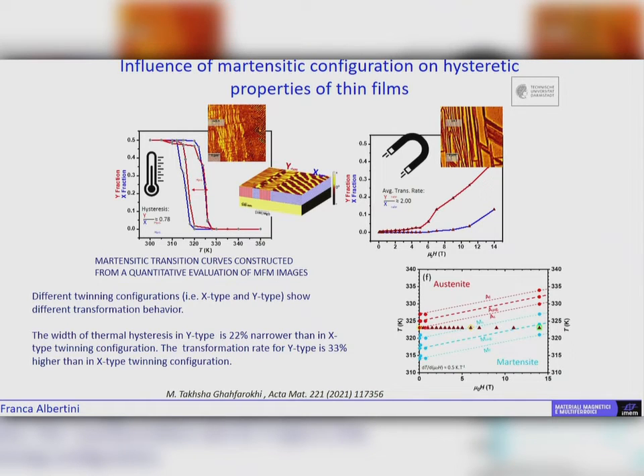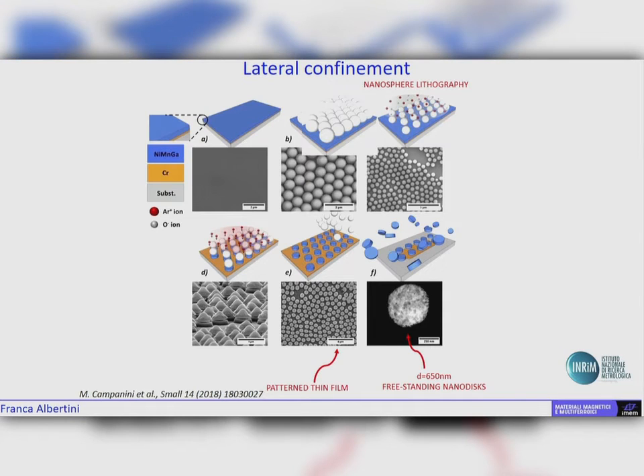And we have seen that the different twinning configurations show different transformation behavior, and that the width of the hysteresis, that has to be reduced as much as possible, is 22% narrower in the one kind of microstructure than in the other. And also, in this case, the transformation rate for Y-type is much higher than the transformation rate for the X-type. So we have obtained some results that can be exploited for many kinds of metamagnetic Heuslers, and some kind of microstructure can be induced or favored to reduce the hysteresis of these materials.